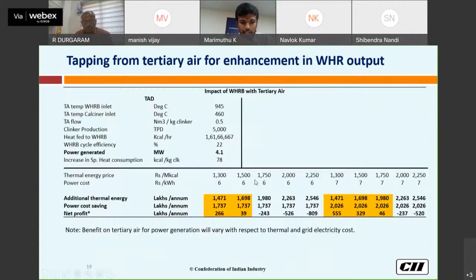So this is the calculation which gives the payback period, the improvement in power generation, as well as savings. So with a drop from 945 to 460 degrees, for 5000 ton production, we will get power generation of around 4.1 megawatt. But the thing is, we need to add more heat input to the calciner because we are extracting heat which would go into the tertiary air to the boiler, so it will increase the specific heat consumption. So the savings calculation is presented there.